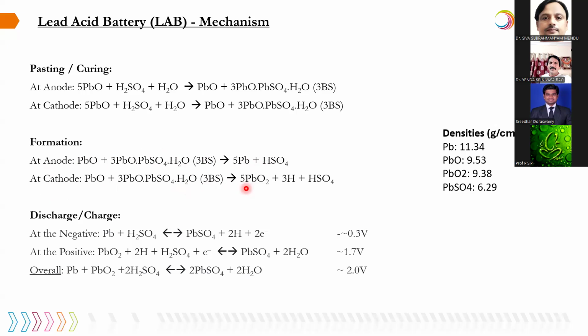If we see, the densities are varied here. So the metallic lead density is 11.34 grams per cubic centimeter, and lead suboxide or lead oxide 9.53. Lead dioxide is 9.38 and lead sulfate is 6.29. Here we can see the densities are varying at different levels, right from pasting to formation and again charge and discharge conditions. So this means the phase transformations happen at each and every cycle in the electrodes.